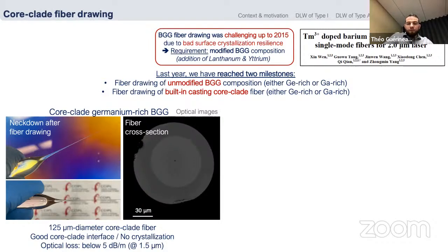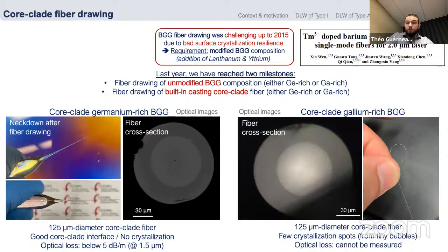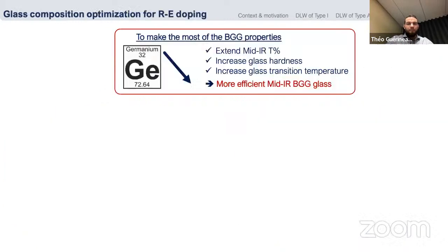We think that we have lower losses, but we couldn't observe them due to the absorption of erbium. And here we have the picture for the gallium-rich BGG. In this case, it's much more tricky to fiber draw gallium-rich BGG. Even if we can easily handle the fiber, we observe the formation of tiny bubbles at the core-clad interface. That was introduced during the glass casting. And these tiny bubbles helped a lot to generate some crystallization spots. Due to that, we cannot measure the losses in these glasses.